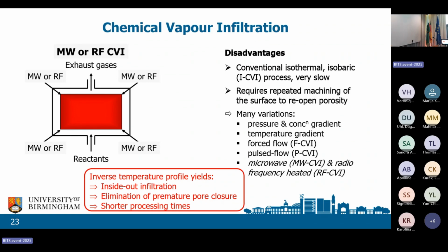Now, what happens is that the inside temperature, you get inside-out infiltration. The inside is the hottest. The outside is the coolest. You get the deposition in the middle of the part, and then it goes outwards. That eliminates premature pore closure. You don't have to stop the process machine and start again. It's one run through, much shorter processing times. With silicon carbide and microwaves, 10 times faster, 100 hours instead of 1,000 hours. With RF and carbon fibers, 40 times faster. You can now do it in 24 hours to make a part.